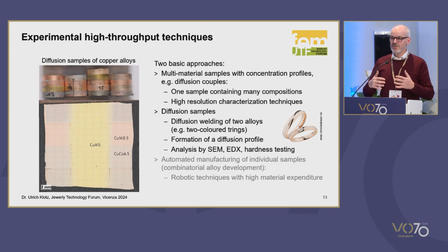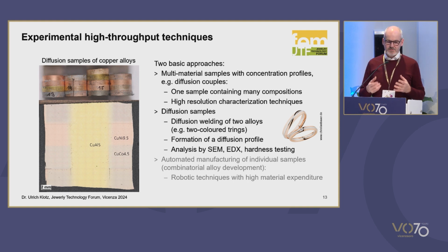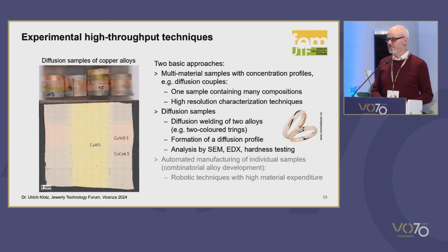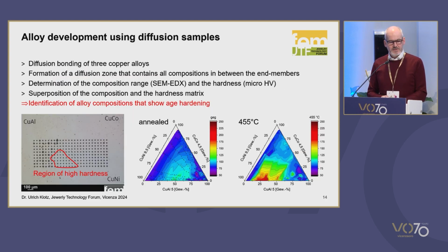And by diffusion, the compositions of these different alloys are mixing. So in this diffusion zone, which is maybe 1 millimeter wide, we get a mixture of all the 3 alloys in this case at the contact point, and we get hundreds of compositions within a very small range. Now we have to measure these compositions, and we can do this in the electron microscope and by microhardness measurement. And this is what we have done here.